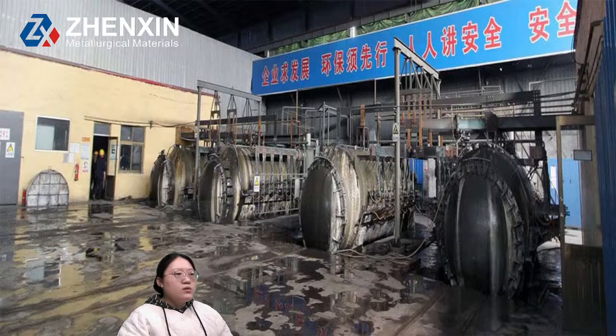There is an important point. The effective magnesium content in iron is very low. It's normally only about 0.03 to 0.05%.